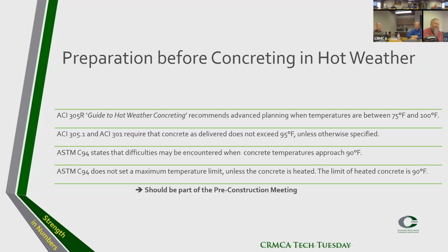Preparation before placing concrete in hot weather. There are some ACI guides. 305, the guide to hot weather concreting, recommends advanced planning when temperatures are between 75 and 100. 305.1 and 301 require that concrete as delivered does not exceed 95 unless it's differently specified. ASTM C94 states that difficulties may be encountered when you go above 90. And ASTM C94 does not set a max temperature unless the concrete is heated. So if the concrete is heated, it may not exceed 90 F. And this should be part of a pre-construction meeting, really important, especially in summer, how to make sure that the concrete that is delivered does not exceed the specified max temperature.